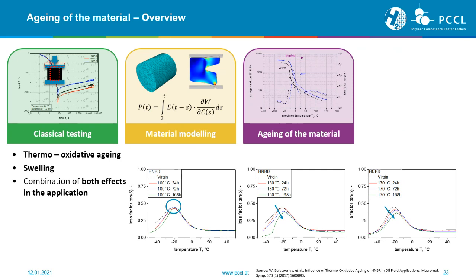As an example, you see here an impact on the loss factor. Based on the dynamic characterization, we've defined storage modulus, loss modulus, dynamic modulus, and loss factor. The loss factor, tangent delta, also represents the damping of the material behavior. And we've studied here the material performance. In this case, one more time HNBR: black line virgin, then red, blue, and green lines aged at 100 degrees for 24 hours, 72, and 168 hours. And then we've increased the temperature from 100 to 150 to 170.